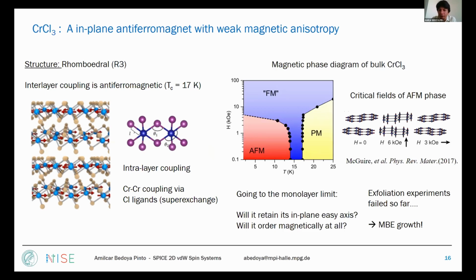This is the phase diagram. In the antiferromagnetic bulk, you require relatively low critical fields to break the antiferromagnetic phase. You can find this data in this reference. You see that the spins are in the plane, but when you apply a perpendicular magnetic field, after a critical value, the spins will follow the direction of the field. The question for us is, what will happen if we go to the monolayer limit?